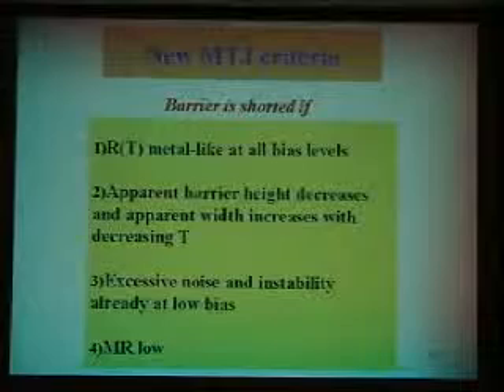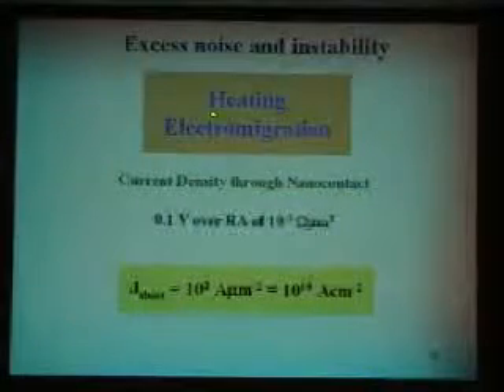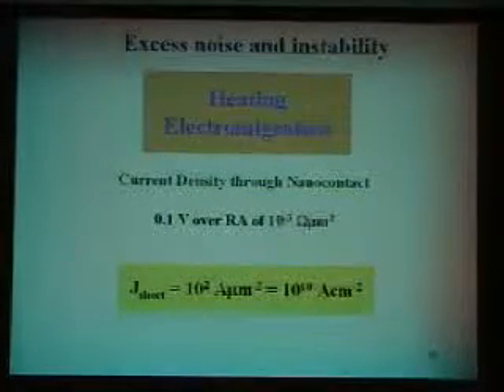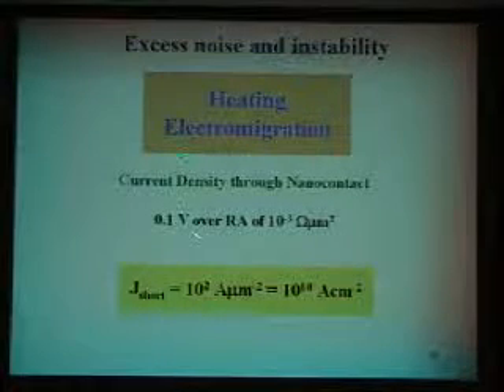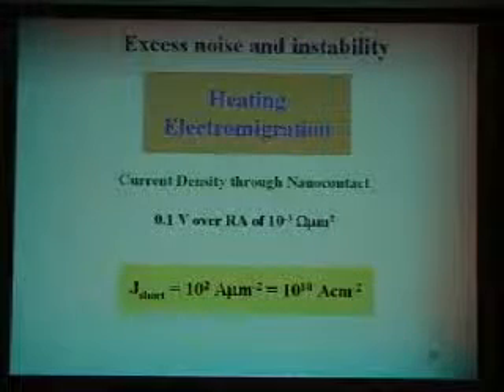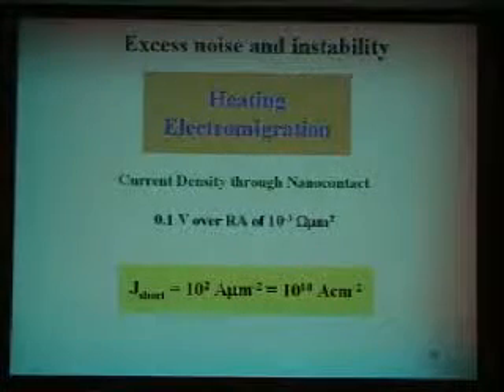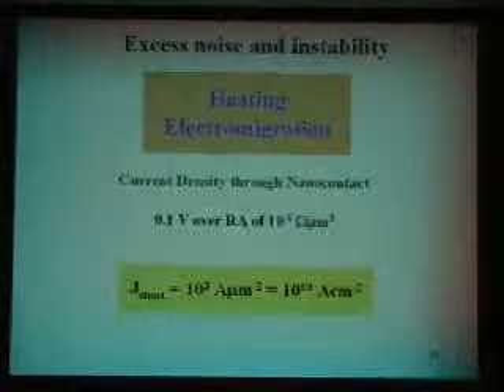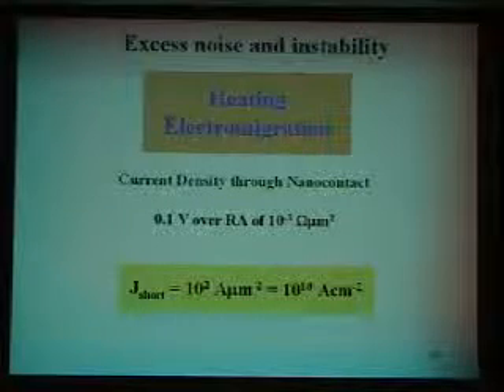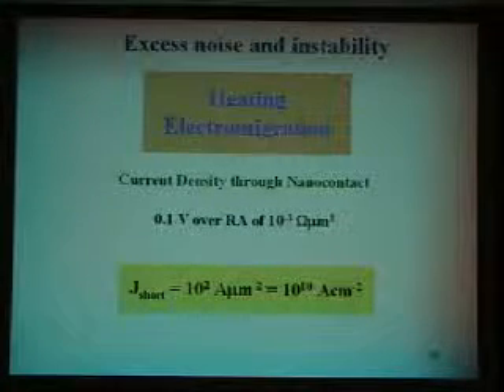You don't want shorts in your device, and the reason for that is very simple. It has to do with heating or electromigration. We're not sure exactly which one of those. But if you do a simple calculation of how many shorts you have, and you can calculate this very easily by just comparing resistances, you find out that the current is huge. It's about 10 to the 10 amps per square centimeter flowing there. Huge current flowing through those shorts, and that's what gives rise to the noise.